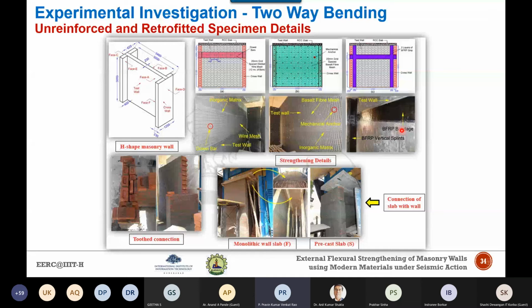Now here you can see that the test wall notations are suffixed by the letter F or S. What are this F and S indicating? They indicate the boundary conditions at the top edge of the wall. The F indicates the walls with integral support at the top, which is obtained by constructing an RCC slab by pouring the concrete directly over the wall. So this represents my rigid diaphragm condition, which I had discussed earlier.